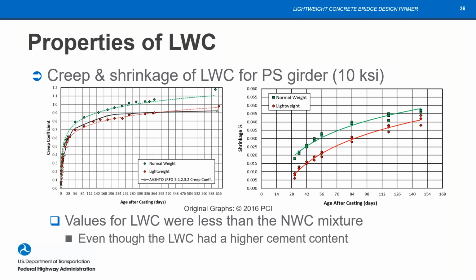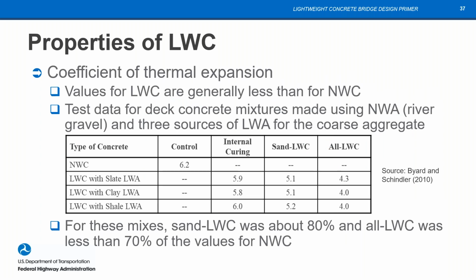That's very surprising because the lightweight concrete actually has almost 25% more cementitious material in it than the normal weight, yet it has a reduced shrinkage. So that's probably due to reduced autogenous shrinkage due to internal curing. That's probably the main thing that's going on there. But it's very surprising. But it's clearly demonstrated here, and it is repeated with other data. So creep and shrinkage are not greater typically for lightweight concrete than they are for normal weight.